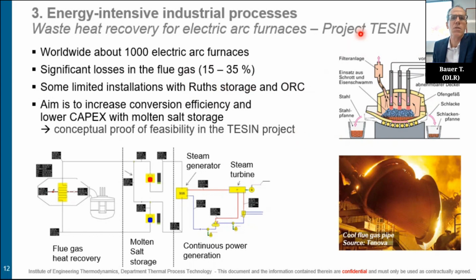And we did, in a project called Tessin, together with the industry, a study of integration of molten salt. This was not demonstrated. This was a conceptual study here. And you would integrate, similarly as here, a heat exchanger for molten salt, and you can store the heat. You would need something like 100 tons of molten salt, not too much. The process time is short, maybe only 15 or 30 minutes of storage. You don't need to bridge very long durations, but then you could bridge this gap when you discharge your furnace, and then you could run a steam turbine continuously.